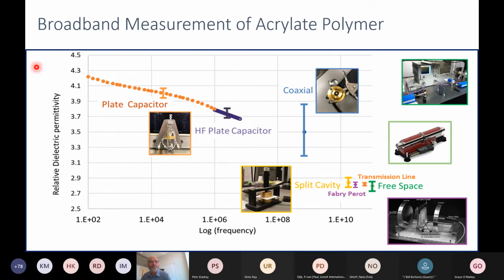The other thing you'll notice is that we have this relaxation. If you ever see an increase in your permittivity as a function of frequency within this range, it's probably not correct. I don't think I've ever seen a material increase its relative permittivity with frequency. That's normally related to inductance or some other error. So you always get some sort of decrease in the permittivity as a function of frequency within this range, right? If you go into the terahertz and above, that's a whole different story.